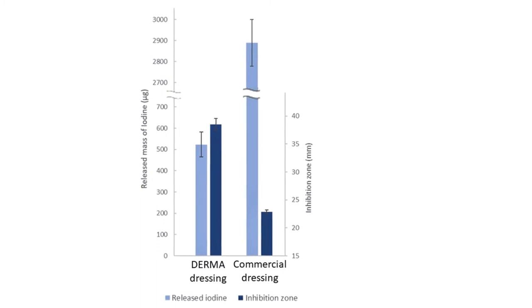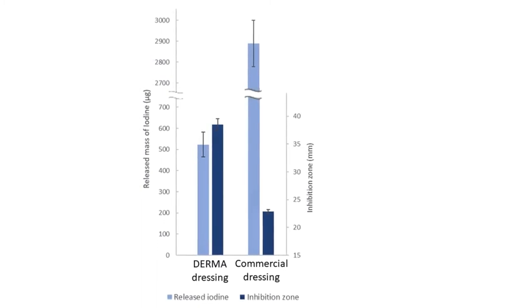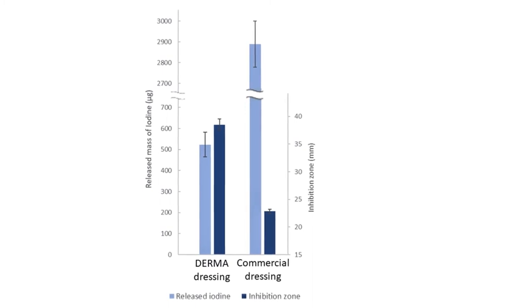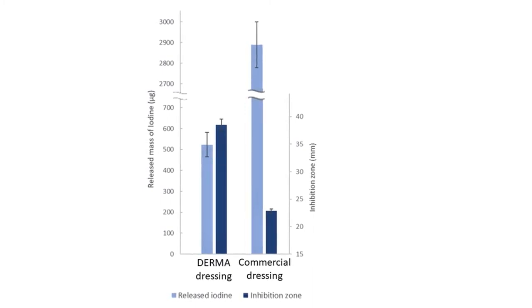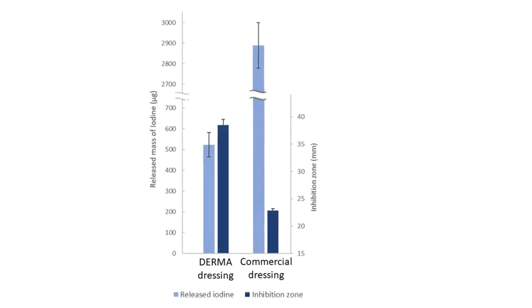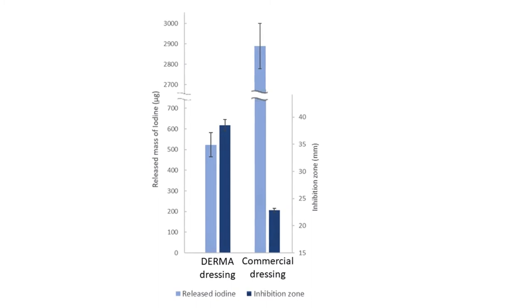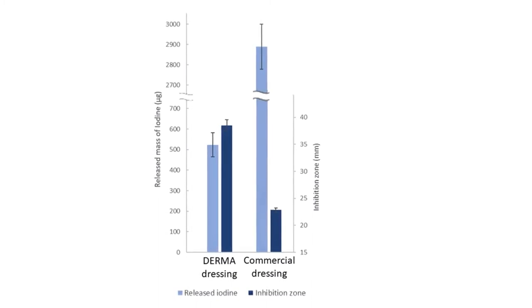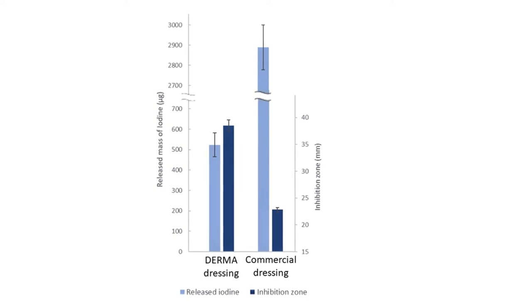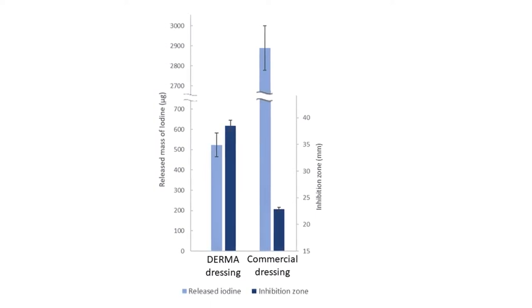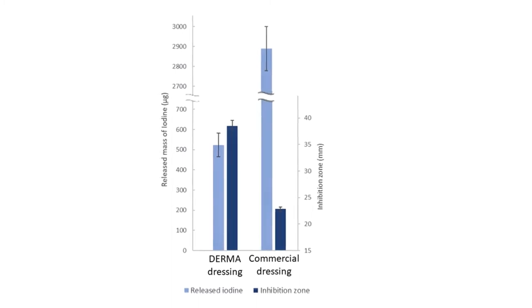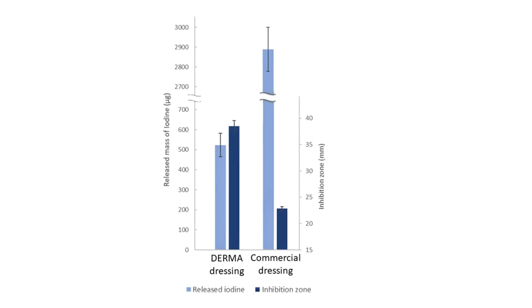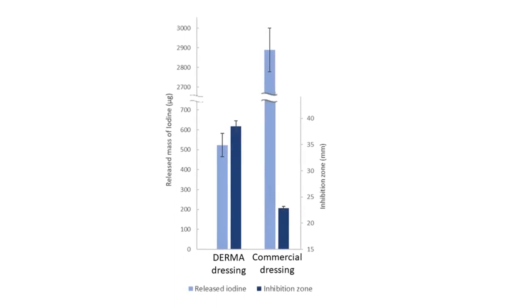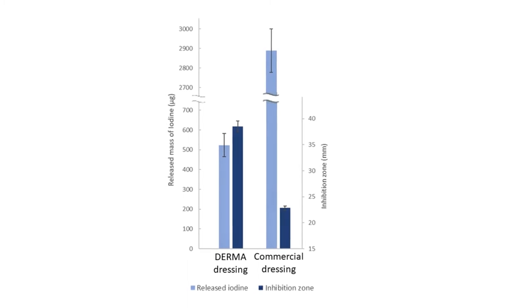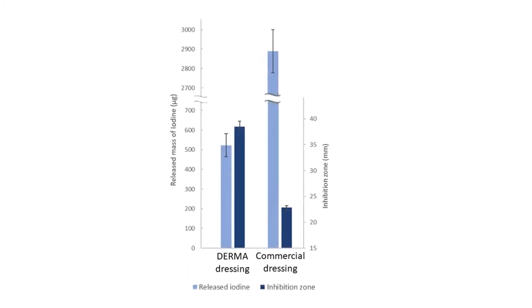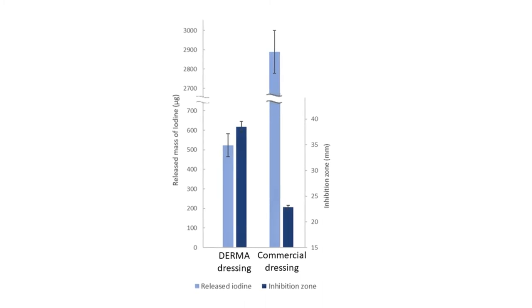In this graph, we can actually see the comparison between DERMA dressing and the commercial dressing in terms of released iodine in light blue and the inhibition zone in dark blue. Here we see that the DERMA material releases less iodine than the commercial dressing, where we see a very big burst release for the commercial dressing. But the inhibition zone of the commercial dressing is a lot smaller than for the DERMA dressing.